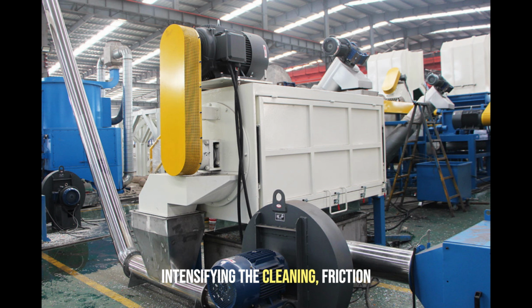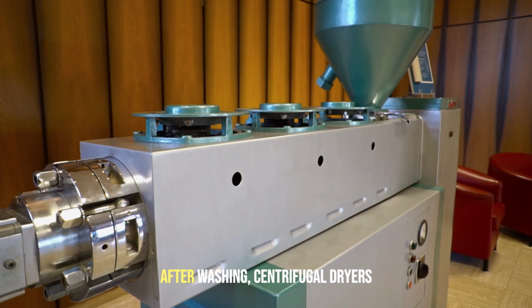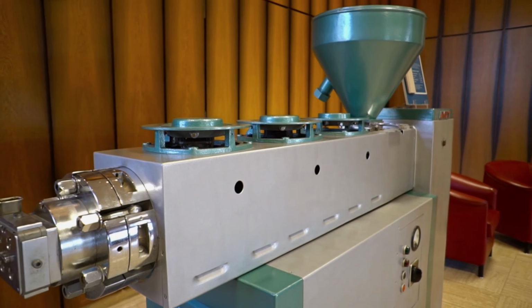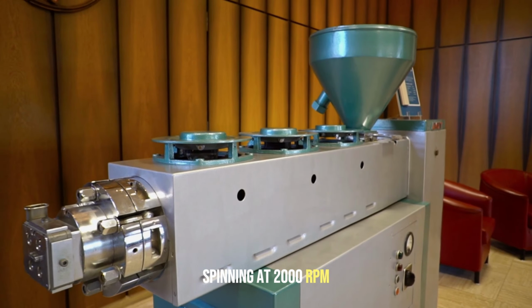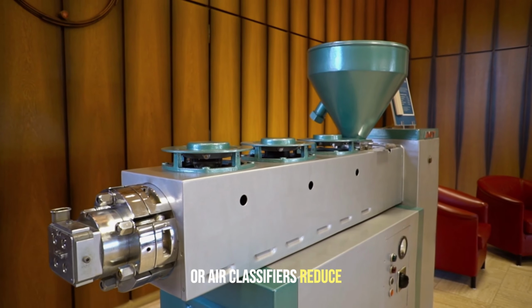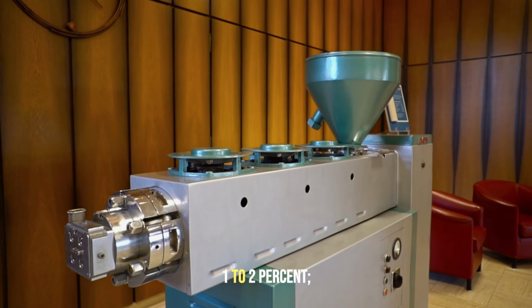Intensifying the cleaning, friction washers with high-speed rotating drums at 1,000 to 1,500 revolutions per minute vigorously tumble the flakes, combining mechanical scrubbing action with high-pressure water sprays to remove ingrained dirt, oils, and residues, often followed by float sink separation tanks based on density differences. After washing, centrifugal dryers spinning at 2,000 revolutions per minute or air classifiers reduce moisture content to under 1 to 2%.